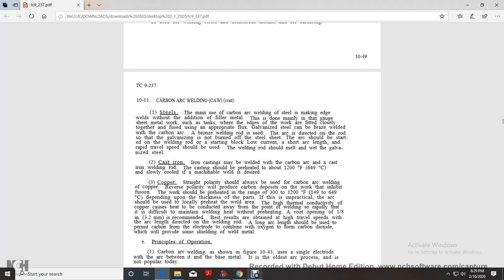Cast iron may be welded with a carbon arc using a cast iron welding rod. The casting should be preheated to about 1200 degrees Fahrenheit and slowly cooled, then machined if desired.